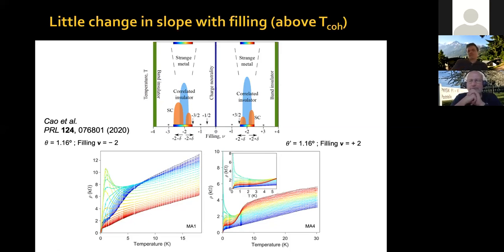Okay, so it's different for transport experiments and for the scanning nanoSQUID techniques and so on. When you do a transport experiment, with the twist angle in the way that I just described, we first look at the band insulator that tells you roughly what the twist angle is. Then we do magnetic field measurements, and the Landau fan diagram tells us what the twist angle is. Now, we do a fitting procedure to determine that density at zero magnetic field to which these lines extrapolate. And you have to determine where these lines that you extrapolate to zero are located. For that, we do a fitting procedure, okay?